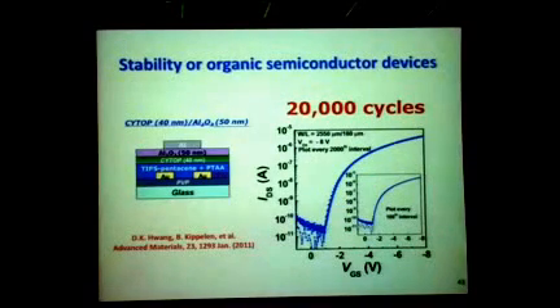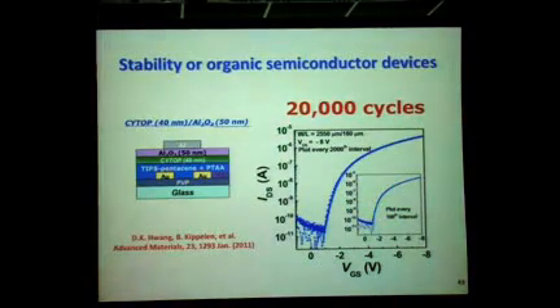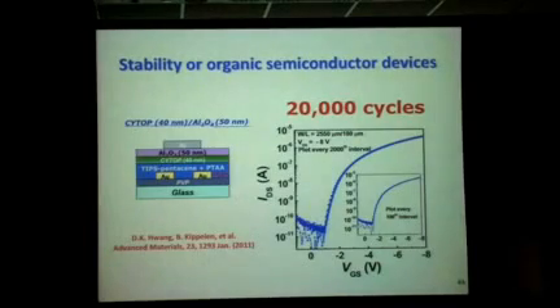What's really nice about these transistors, and totally unanticipated, is that they are extremely stable. You can see here 20,000 on-off cycles measured for these transistors, with no degradation and no shift in the threshold voltage, which is really important.